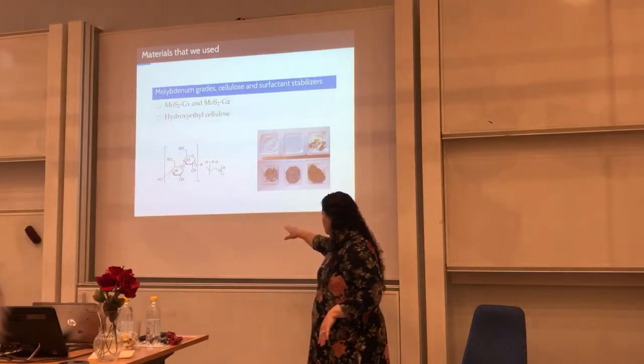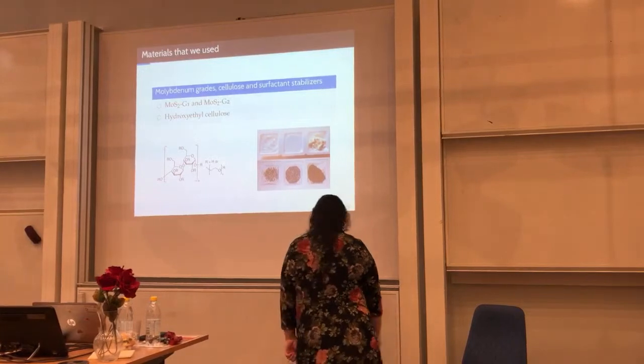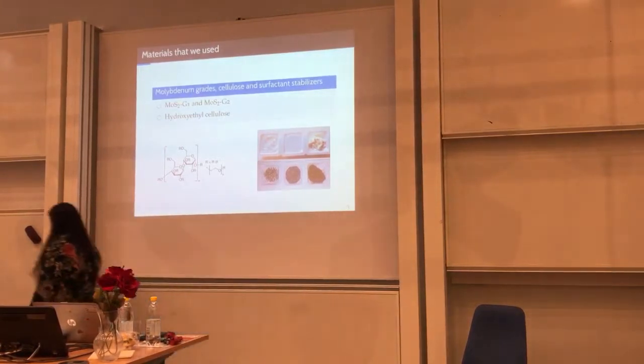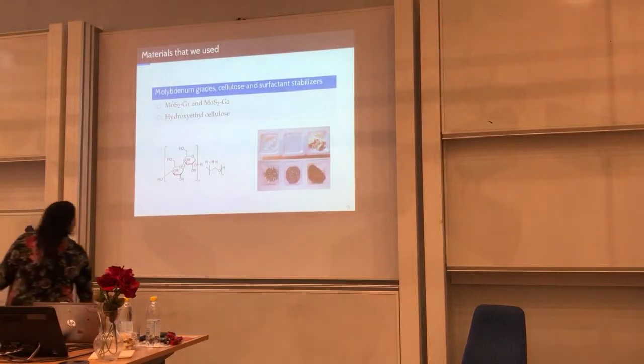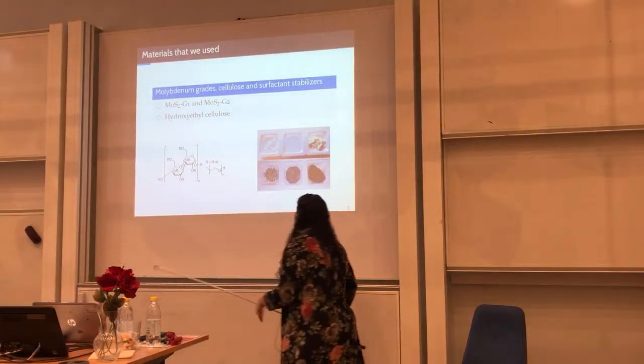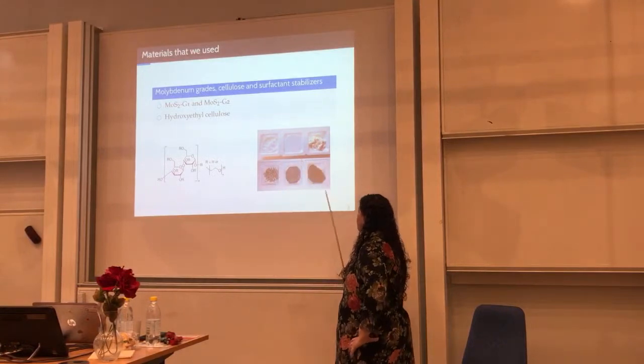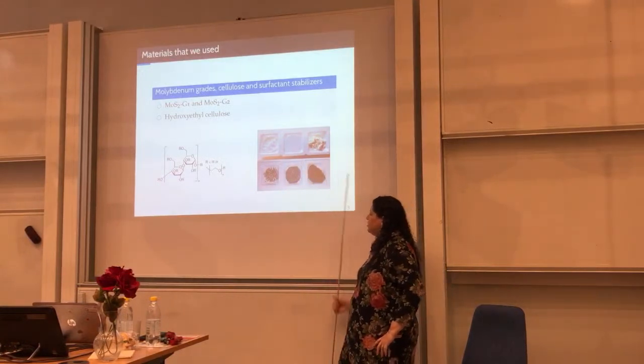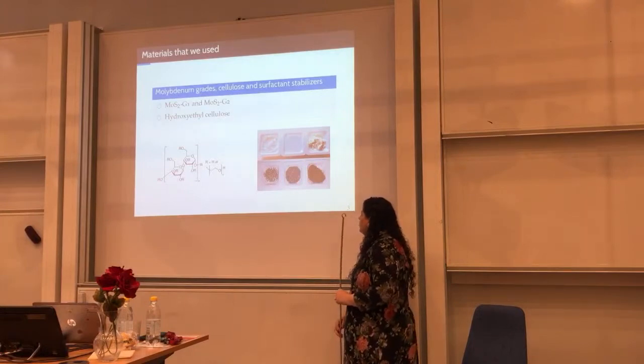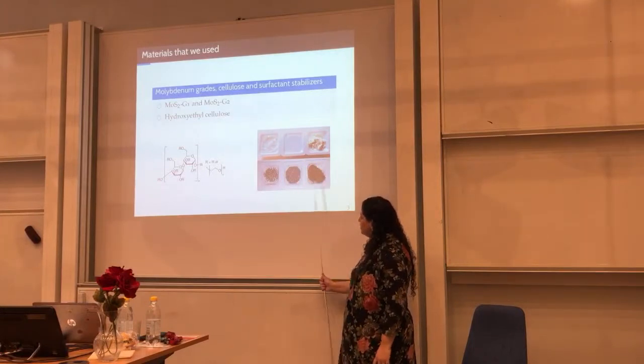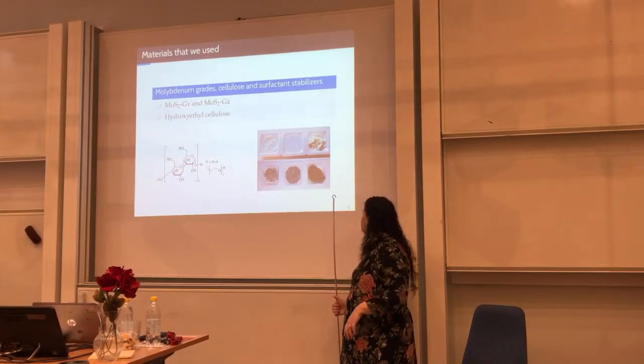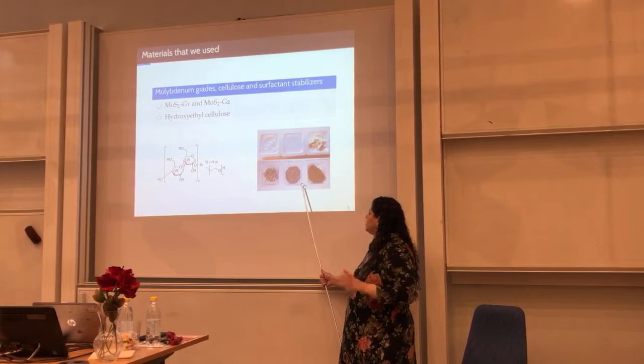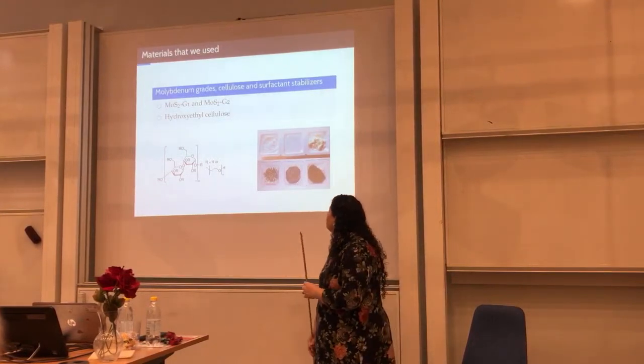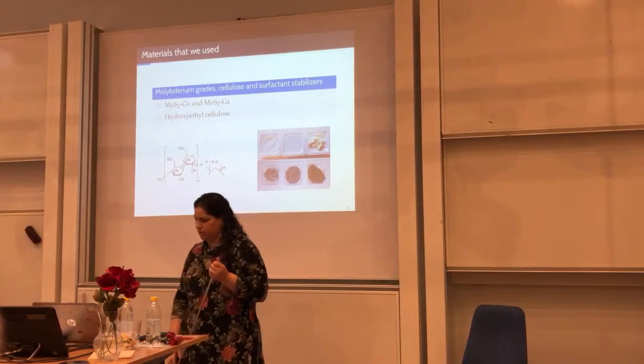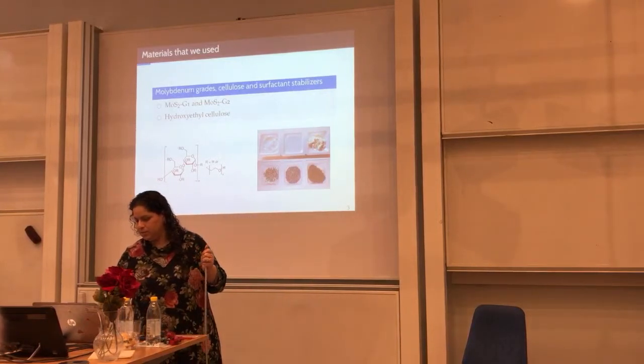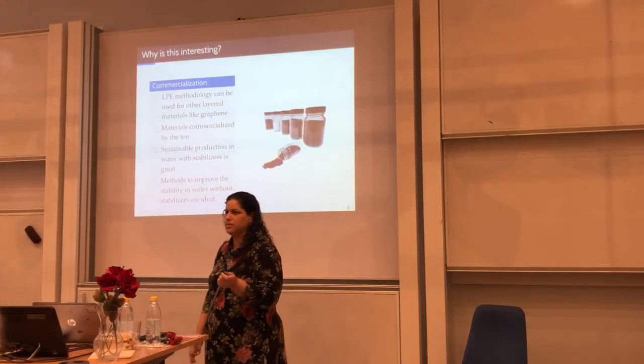These are some pictures of the materials. I have tried to use some nanocellulose, but it was not as effective as the hydroxyethyl cellulose for the purpose I want. And the grades of molybdenum that I use have different particle sizes. One was very, very fine. The other was around 1 micrometer to start with. And this is the molecule of hydroxyethyl cellulose. It's a cellulose that has been modified to be more hydrophilic, so that's why it's interesting for me.